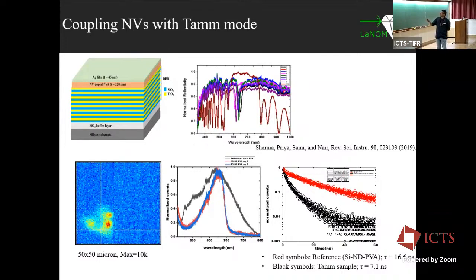Because again, it relates to how your NVs are coupled with the Tamm structure. So it may not be that all NVs are coupled very equally. Even though in the literature, people show that everything is intact, probably that is from one measurement. So it's very important to have statistical measurements, as many NVs as possible, so that you get a complete idea of how these NVs are coupled to the Tamm mode or a cavity mode in general.